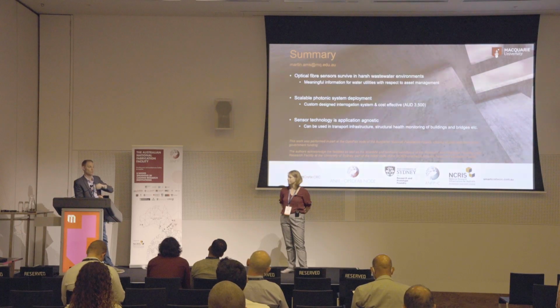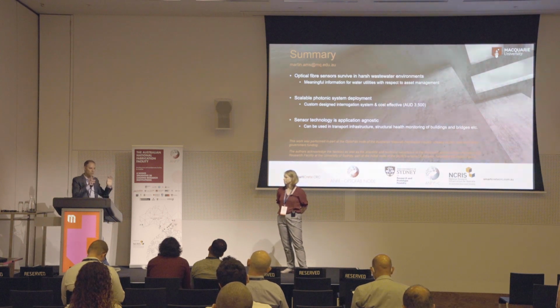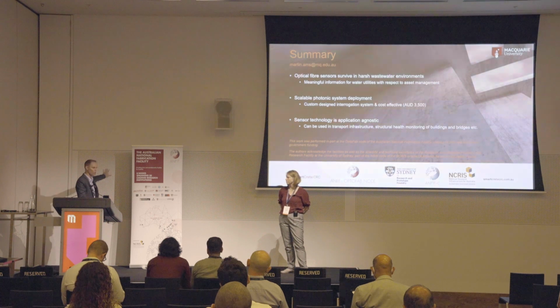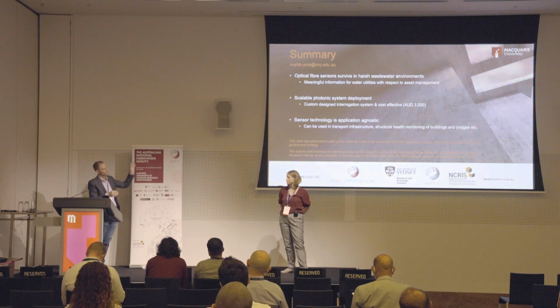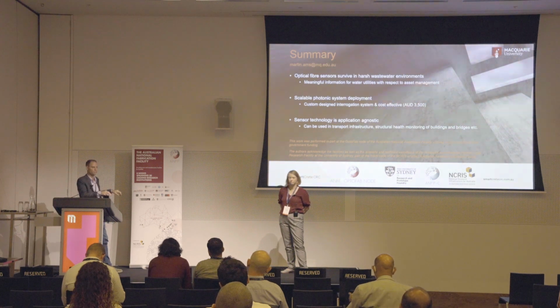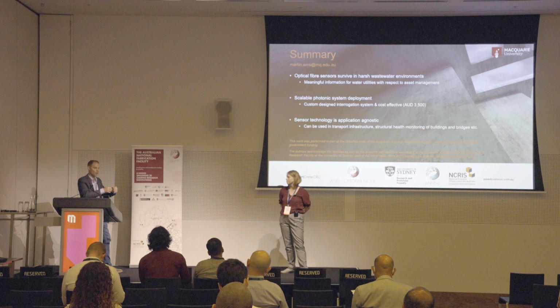I actually want my coupons that I'm putting in the sewer to corrode super fast. I want to pick up events really quickly and then make some sort of informed guess of how that relates to the wall in the environment where I've deployed my sensor. So that video was me with different mixtures trying to find the fastest mixture that can corrode. When I throw it in a gas environment, I hope the bugs grow on it, convert this H2S gas into acid and corrode it. I want it to go fast.